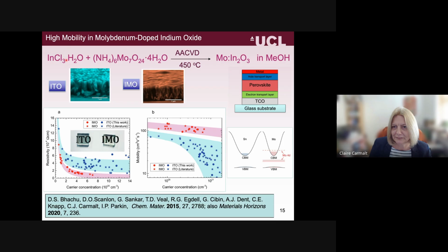So what we did was take indium trichloride and methanol, and then add in dopant amounts of ammonium molybdate, again in methanol, and we created a range of different molybdenum doped indium oxides. And we had a look at that and compared it to literature. And you can see this is a photo of our film, so you can see they're nice and transparent. So this is the ITO and this is the IMO, so the molybdenum doped indium oxide.